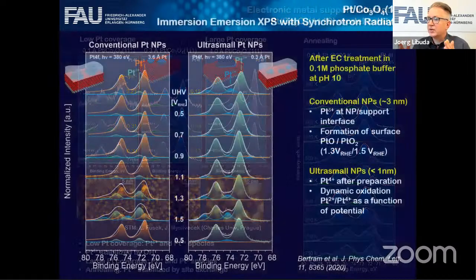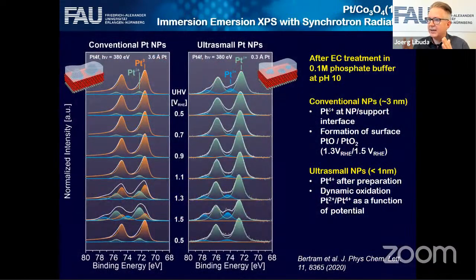Now, I showed you this electrochemical immersion experiment before, and you can use this experiment to follow the oxidation of the platinum particles for this particular model system. So this is exactly this system after treatment in an electrochemical cell at different potentials. Yeah, and this shows that this experiment really works. You can follow the oxidation of the platinum particles as a function of the potential in the electrochemical cell after transfer back to the ultra high vacuum and the beam.